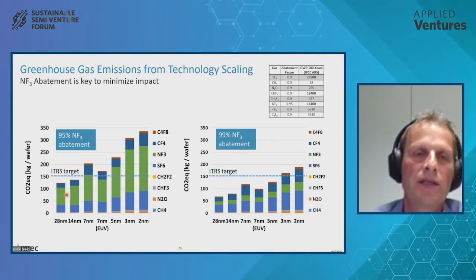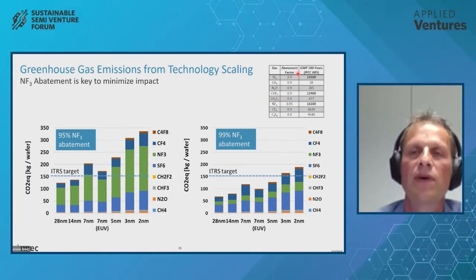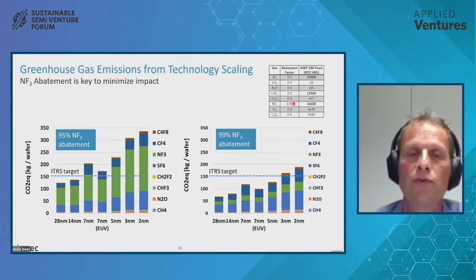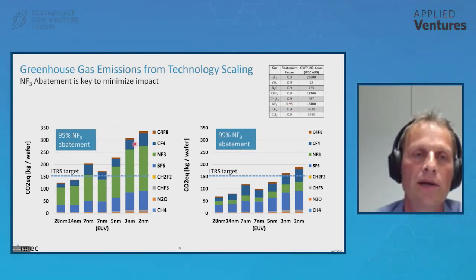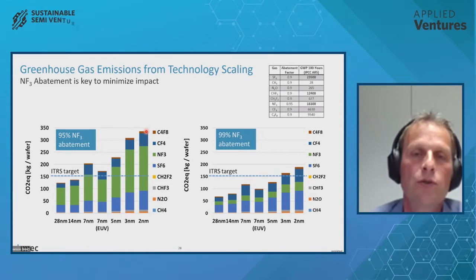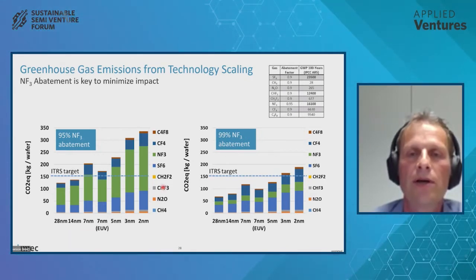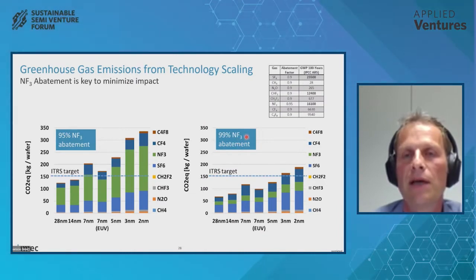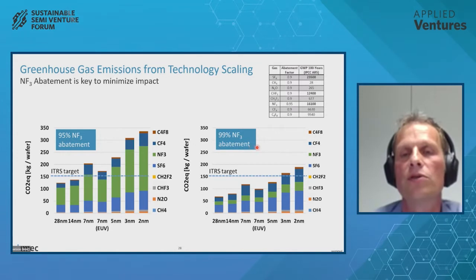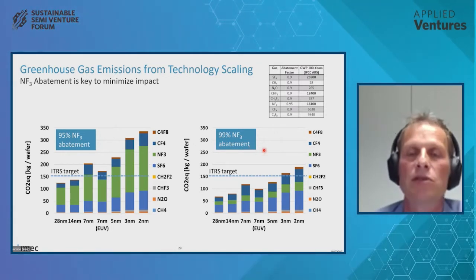So because of that, all of these gases add up, even if in this case we have assumed, as you can see here, abatement factors of 0.9. So 90% of these gases have been removed from the exhaust. And still, these are the numbers that we see. So to get below the targets of the ITRS in 2016, we would need to go to 99% NF3 abatement, which is very energy demanding and will also cause an increase in the emissions because of the abatement system.